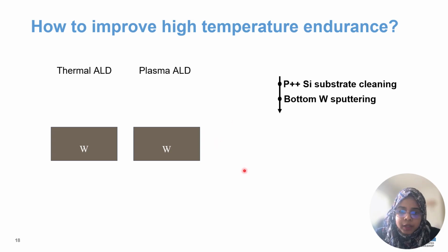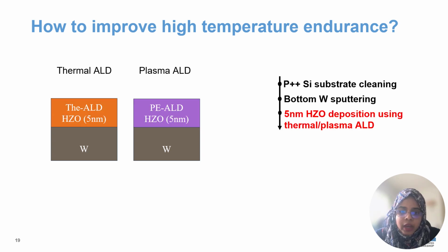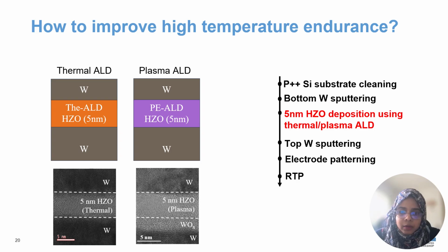Let me first describe the fabrication process of the devices that we are using in this study. We are comparing a thermal ALD sample and a plasma ALD sample. On both of them, we start with sputtering a tungsten bottom electrode on a silicon substrate, and then we deposit a 5 nanometer hafnium zirconium oxide ferroelectric film. The difference between these two is that in thermal ALD, we use water as the oxidant in the ALD process, and in the plasma ALD process, we use oxygen plasma as the oxidant. This is the only difference between these two devices. Next, we sputter the top tungsten electrode to get the capacitor-like structure.